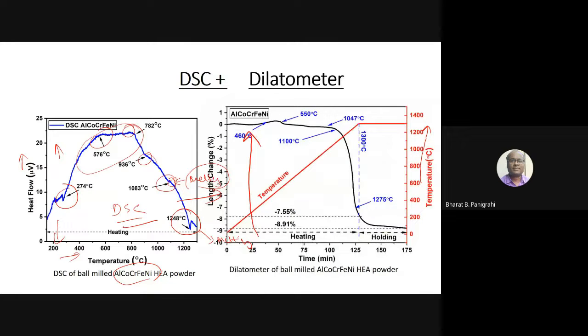There is another technique called dilatometer, which essentially tells you, as you keep heating the sample, you will see a huge shrinkage here. So this is the sample. You make a compact. What does dilatometry mean? Dilatometry is used for thermal expansion measurement. So you have a powder which you make into a compact, or we call it a pellet. When you heat it, the material goes through expansion and shrinkage. If the material has to be sintered, that means you are going to see shrinkage. Sintering leads to shrinkage.